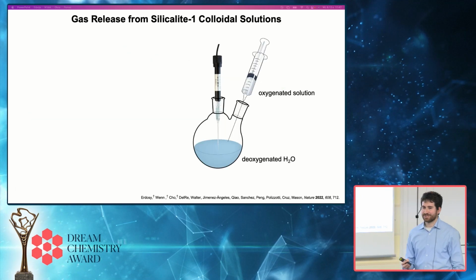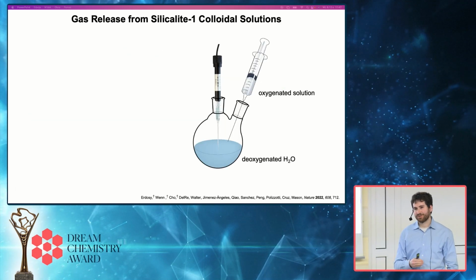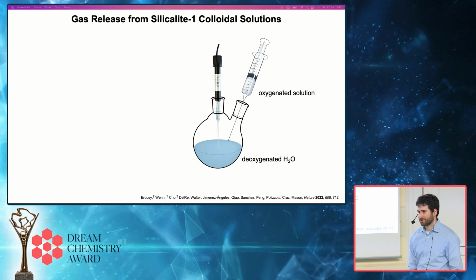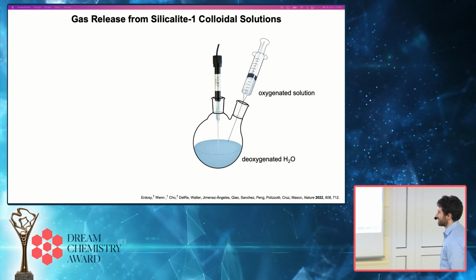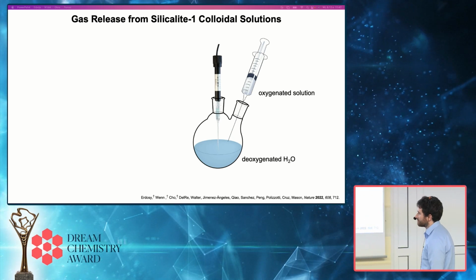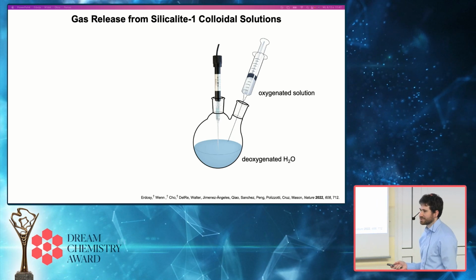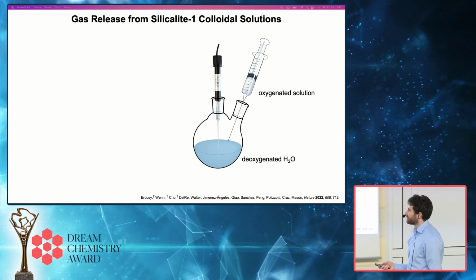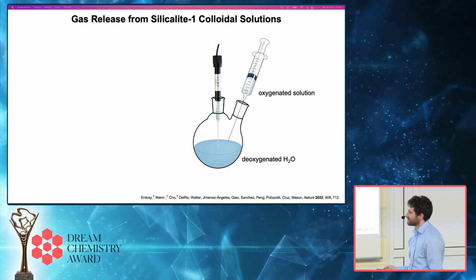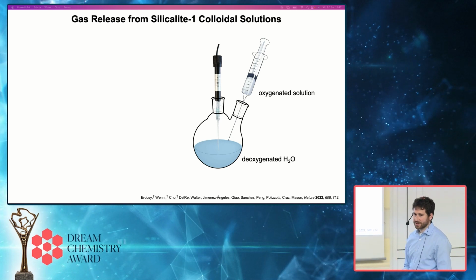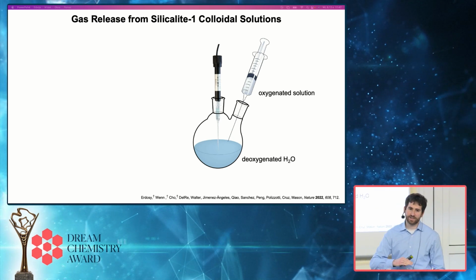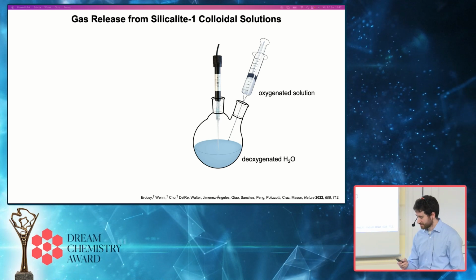So then one of the next things we wanted to do was demonstrate not only that we could absorb gas molecules, but that we could actually confirm that we could release them, and to evaluate, at least to some extent, the kinetics of gas release. And so to do that, we took oxygenated solutions, so oxygenated dispersions of our porous materials, and injected them into deoxygenated water, and then used an oxygen electrode to quantify exactly how much oxygen is released.